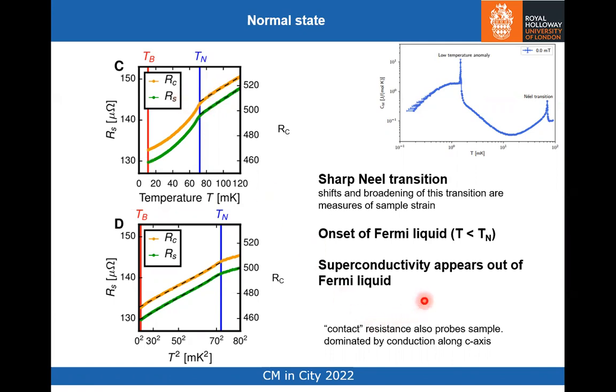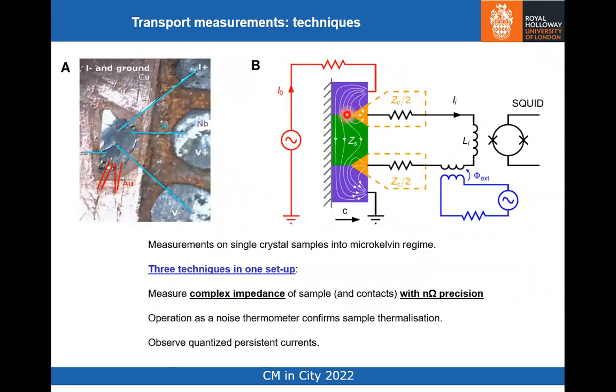So that when the superconductivity appears, it's appearing out of a Fermi liquid. In this regime, at low magnetic fields, this is not superconductivity in a strange metal. It is superconductivity appearing out of a Fermi liquid. And we see these behaviors both in the sample resistance and in the contact resistance, so both in green and orange. So that's telling us that the contact resistance is also probing the sample and contributing to this so-called contact resistance. That's why I put inverted commas around "contact". So that's denoted here in this cartoon.